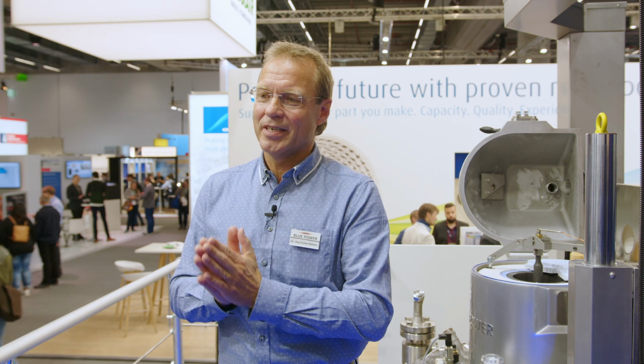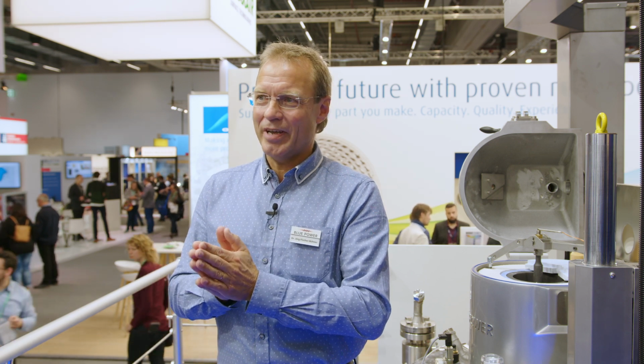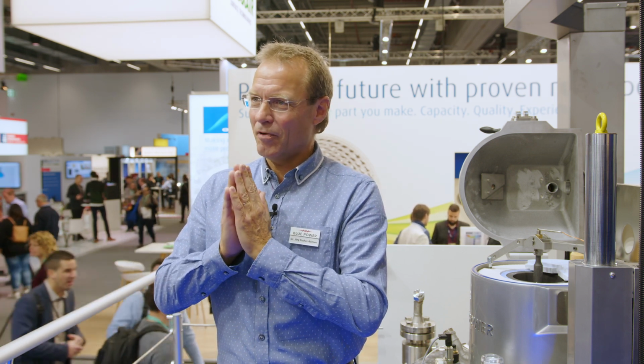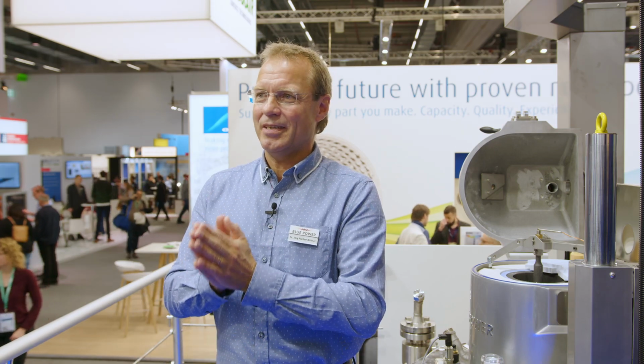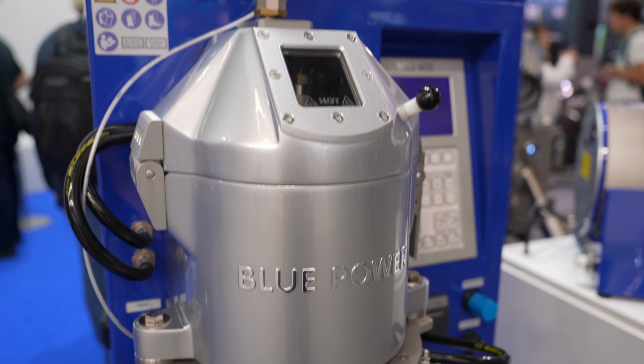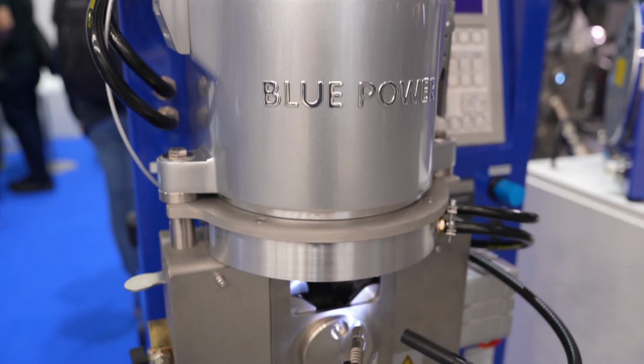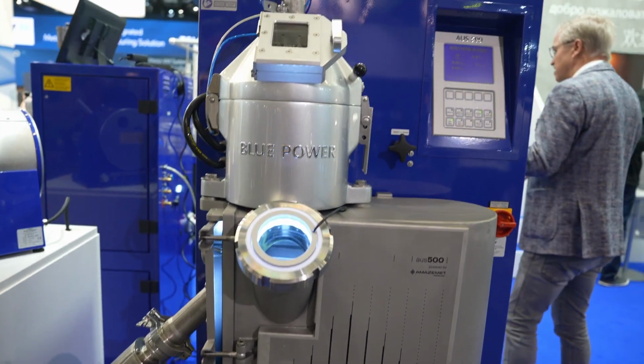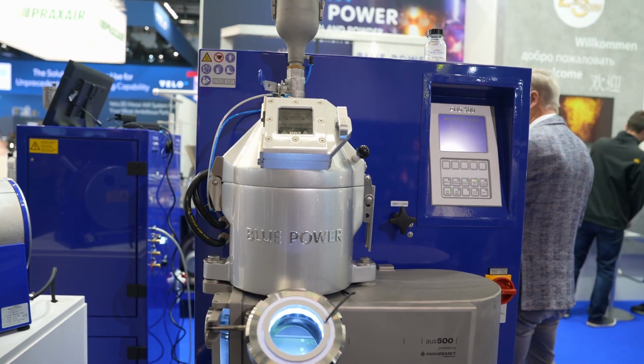The good news is, when we started to work on our atomizer, we have, from the beginning, looked at very good clean out and very low losses. So the system was, from the beginning, designed for that, using highly polished surfaces wherever possible and avoiding undercuts and traps where powder can be lost.